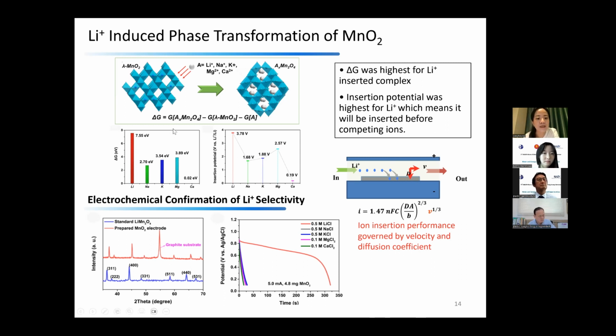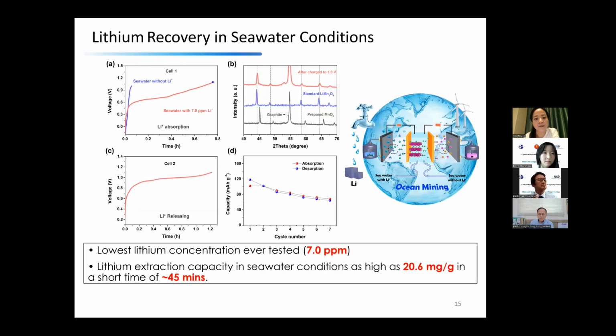And that will be the important feature for the structure. And then also, we have realized the lowest lithium concentration tested among all similar devices or similar equipment, which is 7 ppm. And then the lithium extraction capacity for seawater condition can be as high as 20.6 milligram per gram in a very short time of 45 minutes.